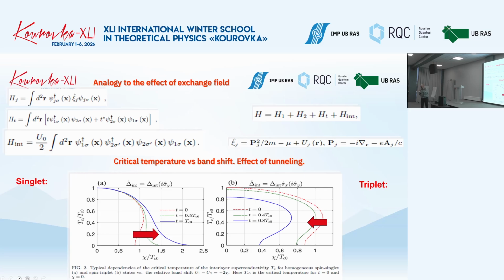Now, homogeneous phase diagrams: you see the critical temperature as a function of chi. Chi is the shift of the bands. It's like the exchange field. You see this red curve is in fact very similar to the picture from the textbook which I have shown you before. But when we switch on the tunneling, you can see that the curve changes. It becomes like the blue one, and this picture is for homogeneous triplet pairing. One interesting thing is that, considering triplet pairing, you can observe that increasing the tunneling gives some suppression of the critical temperature.